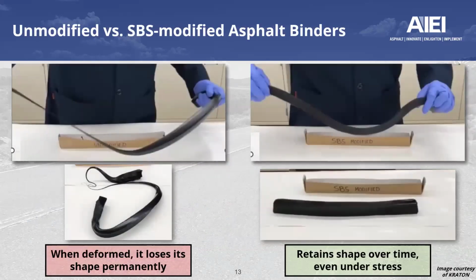This is a couple of pictures of an unmodified binder versus an SBS modified asphalt binder. The images are courtesy of Kraton. The first on the left is an asphalt binder that was unmodified, neat, that was poured, that beam was poured, and it loses its shape permanently. However, on the right, this is a sample of an asphalt binder that was modified with SBS, and it retains shape over time even under stress.